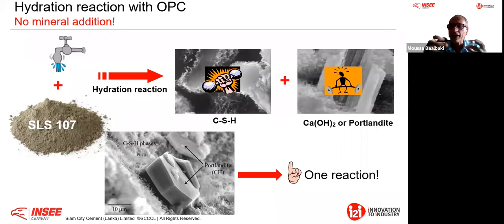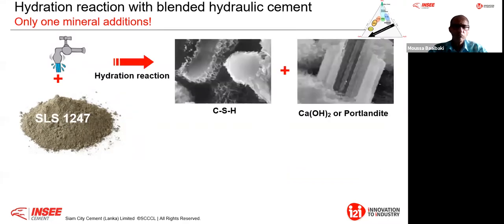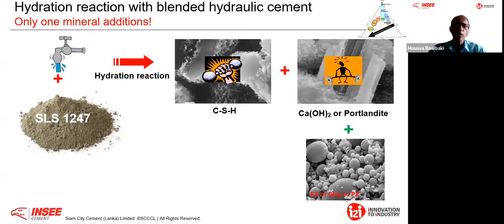Otherwise, you can lose the cohesiveness. You have some issue in fresh or hardened concrete properties. Therefore, now when I come, for example, to the blended hydraulic cement, the 1247, the same, I have clinker. Therefore, if I mix this cement with water, I will get the same reaction, with calcium silicate hydrate and Portlandite. One will give me strength, and one will give me the problem, what I call the challenge.